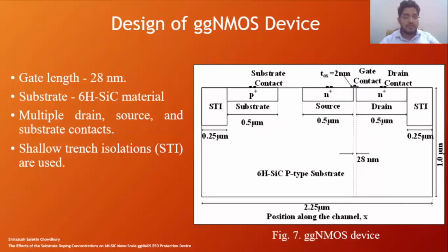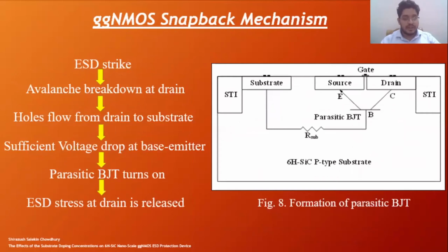The figure shows the proposed device structure. The gate length of the device is 28 nanometers. The material 6H silicon carbide is used as the substrate of the device. Multiple drain, source, and substrate contacts are used to reduce current density. At the edges of the device, shallow trench isolations are used to avoid leakage current among the adjacent devices.